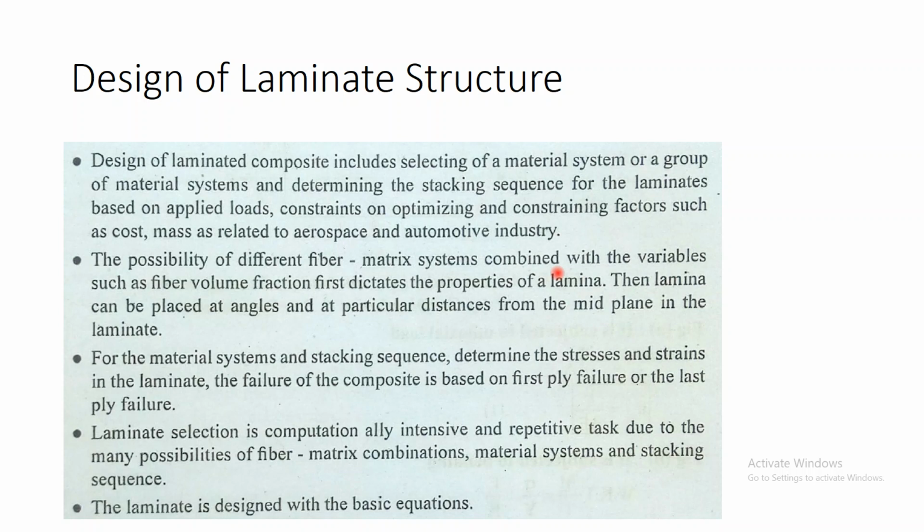In addition to that, there is the material stacking sequence, that is, the angle stacking sequence, and the dependency of the stresses and strains that we calculate on this sequence. And we should apply the failure theory for the composites to see whether it is going to fail or not. Usually the failure theory can be applied to the failure of the first ply as well as the failure of the last ply. Ply is nothing but the lamina.